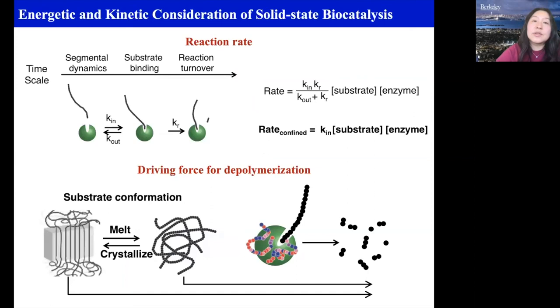And this, again, goes into how we're going to catalyze a reaction in the solid state. So typically, if you treat it as a two-stage process, you form this intermediate by substrate diffusion in and diffusion out to reach an intermediate equilibrium, and then the reaction proceeds forward. And if you look into the overall rate, it depends on the diffusion rate, the K in, K out, as well as the reaction rate. So what you see is that if the diffusion rate is really slow, then the reaction becomes diffusion limited, and it's really about how you can get that substrate into the enzyme mouth to initiate the reaction. And so this gives us a possibility to kinetically modulate the system.